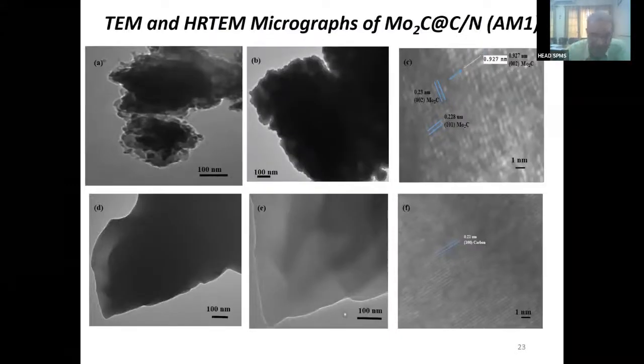So you can see the lattice fringing. Through lattice fringing, we have already confirmed that there are carbon sources. There is Mo2C here. You can see different planes. We have confirmed that this exists here: 002 plane of Mo2C from the lattice fringing, 101 plane of the Mo2C, 002 plane of the Mo2C. So we have confirmed all these things from the TEM microstructure now.